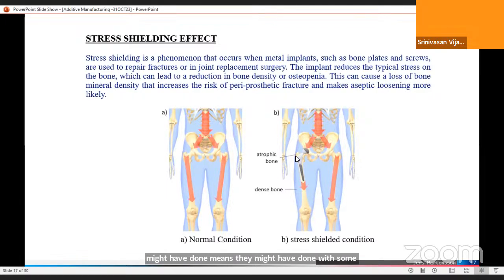That is, they might have increased the surface roughness. I have just gathered this from a journal where they modified the surface roughness according to the adjacent bone for the stress shielding effect. But nowadays, we clearly have the solution that the stress shielding effect can be reduced by the additive manufacturing process. Let me explain how we can.